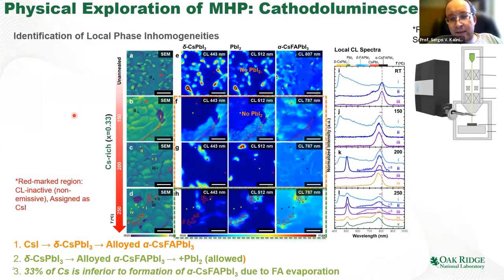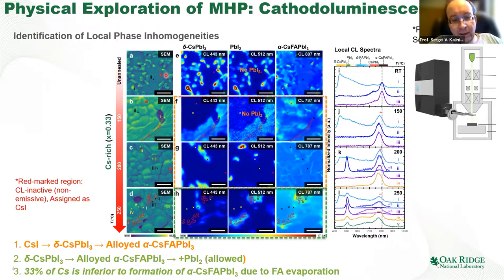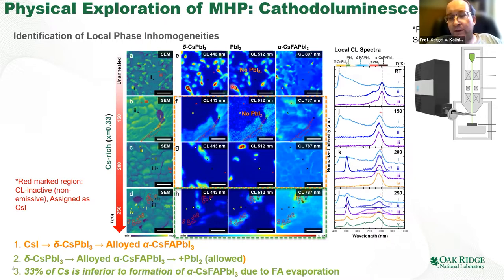They can do a slightly different type of experiment — take the same perovskite film and bring it to a cathodoluminescence setup, where you shine the electron beam on the sample and detect the light emitted locally. Light emission from the hybrid perovskite tells you about what phase it is, what the strain effects are, and the compositions — the usual band gap engineering. One thing we find is that a film that looks absolutely normal under SEM or AFM actually has very significant inhomogeneity. The question we asked: can we establish the relationship between this local chemical and physical inhomogeneity and transport properties — the IV behavior with and without light?